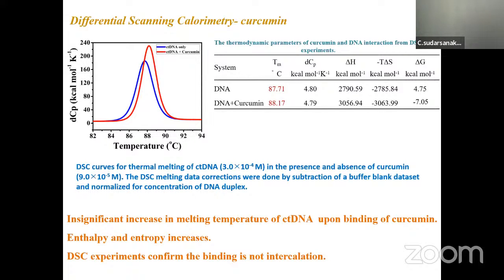If low energy is enough to make the drug come out of the minor groove of the DNA, that indicates groove binding. So the red one shows the DNA with curcumin, and the blue one shows the DNA only. There is not much change in the calorimetric absorption at the melting.